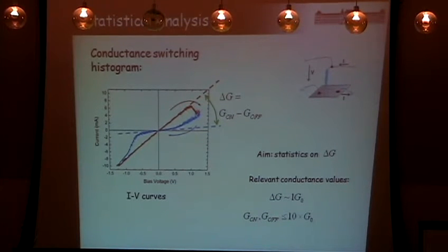The curve reminds me more of what an oxide does than of diffusion in the silver structure. Because on sulfide, for example, the jump is much more pronounced than in your curve, and this is exactly what we see for oxide. So are you sure that you're not switching the tungsten tip, or that you haven't oxidized the silver?